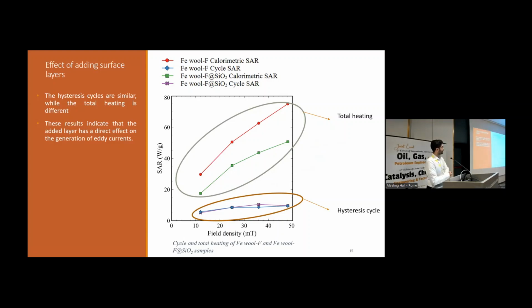To better understand what's happening, we did the following measurements. So we took iron wool with nothing on top, and then iron wool with silica. And we did one total heating measurement and one hysteresis cycle measurement. And what's really interesting is that for the hysteresis cycles, we have the same measurements for both the regular iron wool and the iron wool with the silica coating.